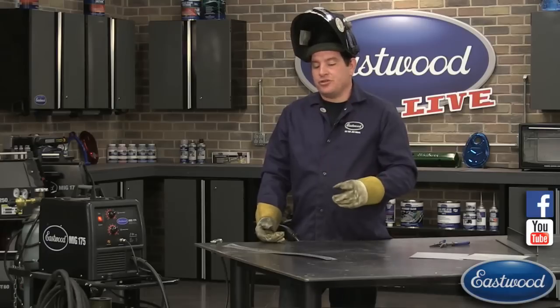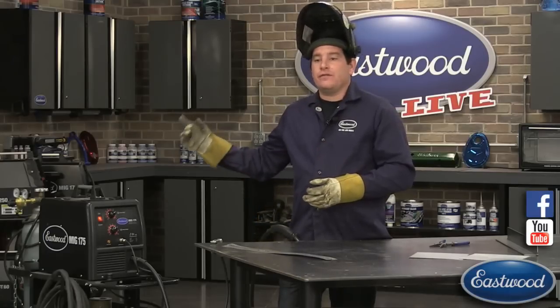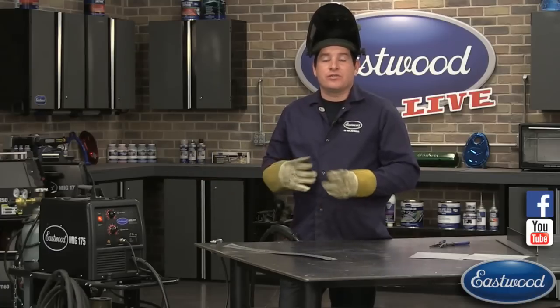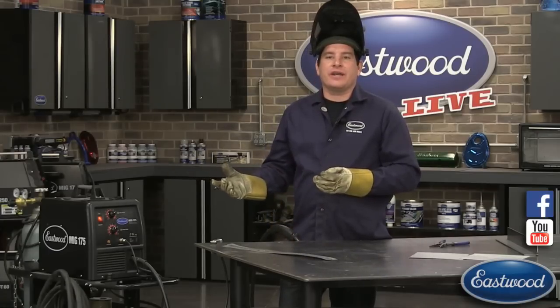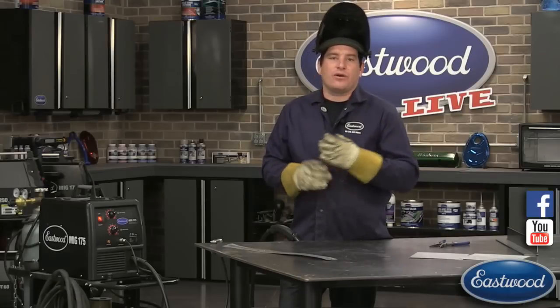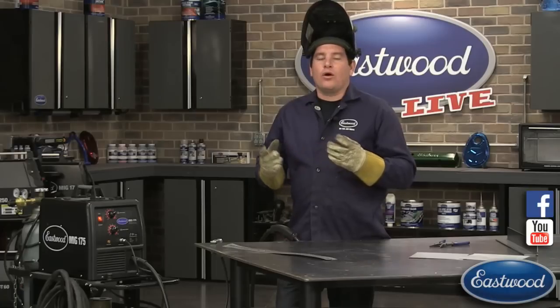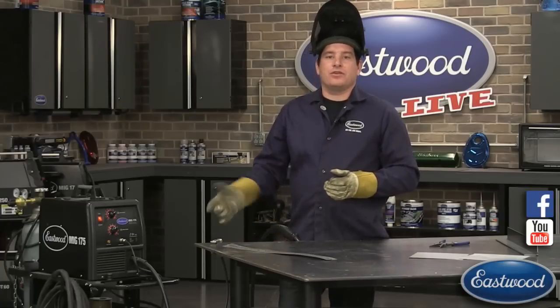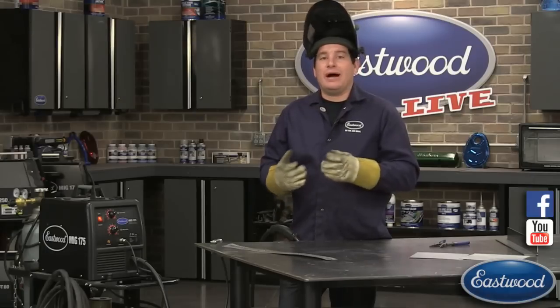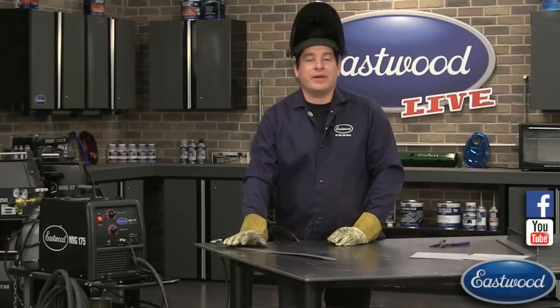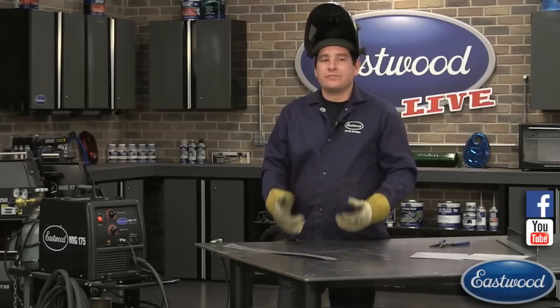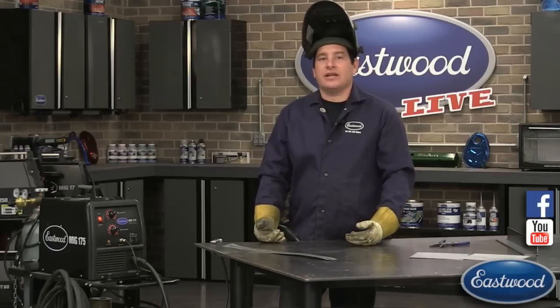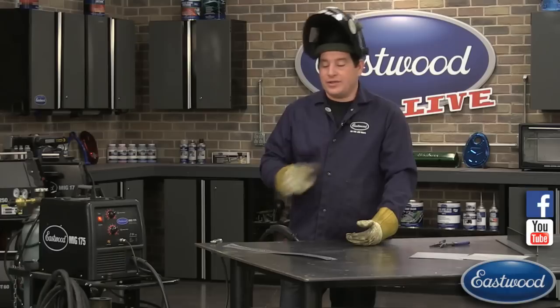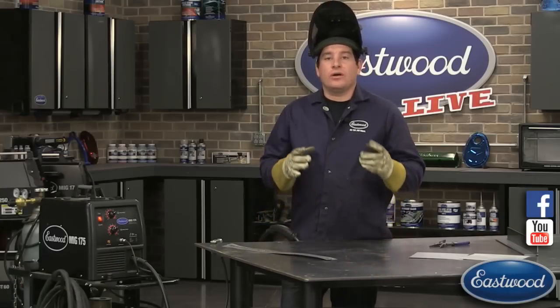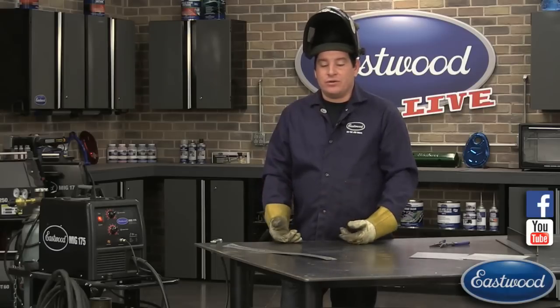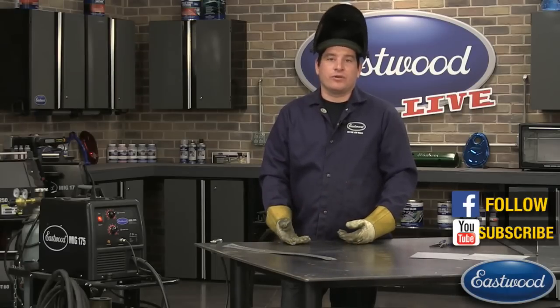What you're trying to do when you're doing sheet metal is match the filler material, or the wire, as close as you can to the thickness of what you're welding. So if you put .035 wire in there, that's another reason I don't really like flux-core, is flux-core .035 is about the thinnest you can get. .035 is thicker than the material that you're welding, so you have to turn the welder up hotter than required to melt the base metal, to melt the actual welding wire. So it creates more warpage, starts blowing holes in the panel. It's not as nice. So .023 wire is pretty darn close to 20 gauge, which is what we're welding here. It doesn't require a lot more heat to melt it into the panel. So that's what I prefer to use. It's really nice, flows really well. So that's a good question though.